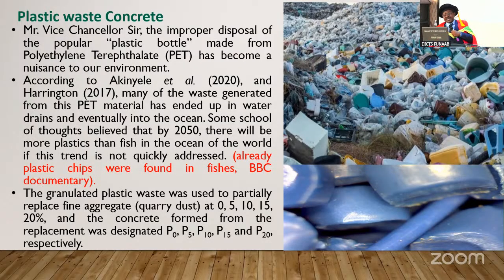In fact, some time ago, I watched a documentary on BBC where some fish were caught, and by the time they caught them, they found some plastic particles inside the fish. It's so that already we have started eating plastic from our fishes. So we have to be very careful the way we dispose of all this plastic. Now, what did we do? The ground plastic waste was used to partially replace fine aggregate in our concrete at 0, 5, 10, 15, and 20%, and the concrete formed from it was coded P0, P5, P10, up to P20.